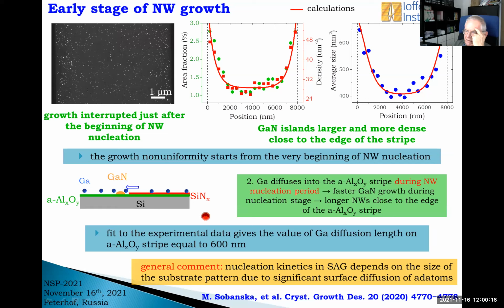And again, we are grateful to Vladimir and Dr. Sobanska for developing a model describing this phenomenon. All these lines which are here on the plots are results of calculation, and fitting gives us an experimental value of gallium diffusion length on aluminum oxide stripes, which equals 600 nanometers. Okay, general comment is that nucleation kinetics depends on the size, and this is important to keep in mind.